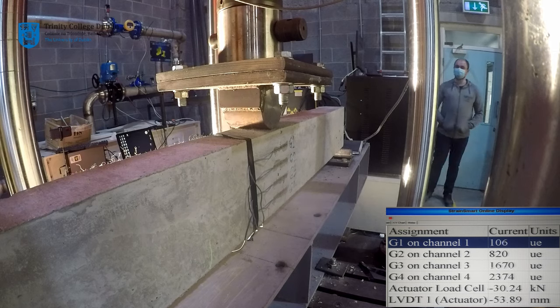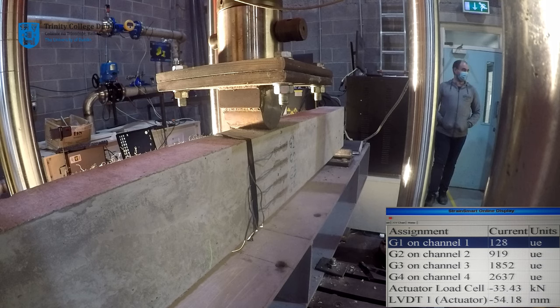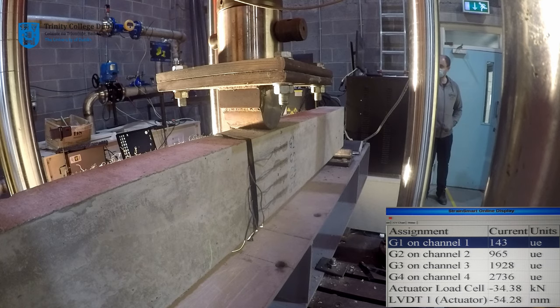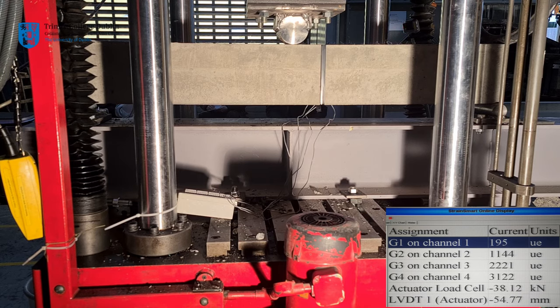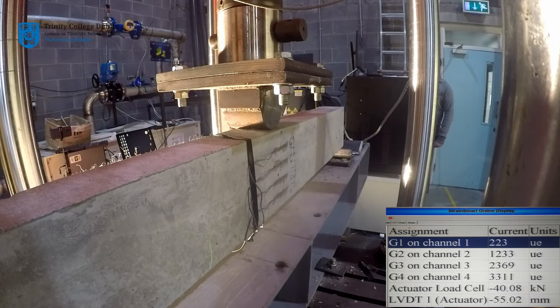Additional cracks will then develop at other locations as the tensile stresses there also begin to exceed the capacity of the concrete. This will first occur near to mid-span, whilst later cracks will develop further from the central region. Tension cracks will gradually widen as the beam bends further, and the concrete and steel at the bottom of the beam stretches in tension. They will also increase in depth as strain values further from the bottom also exceed the capacity of the concrete. Please note the location and order of formation of the tension cracks on the beam, as you will need this information for part 2 of your report. The number displayed on screen next to the crack indicates the order of formation.